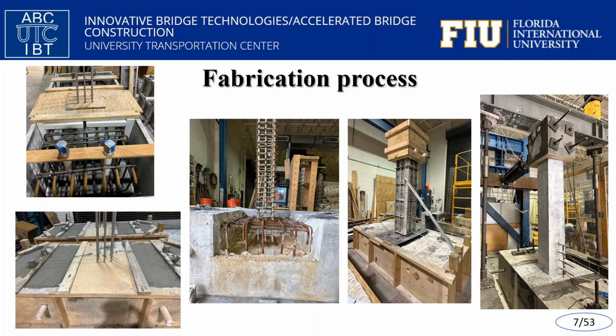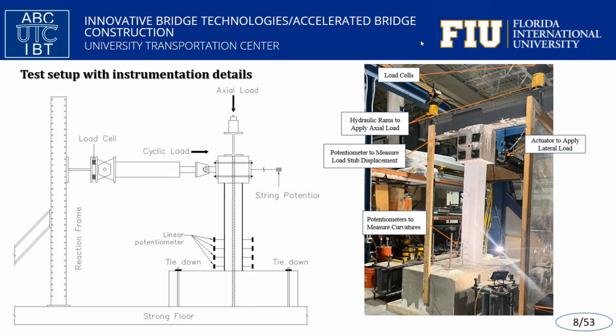It should be noted that UHPC footing was considered for all specimens to better understand the behavior of the plastic hinge. Only the representative part of the foundation below the column was cast with UHPC, and normal strength concrete was used for the rest of it. Here you can see the test setup which we used to apply axial and cyclic lateral loading.